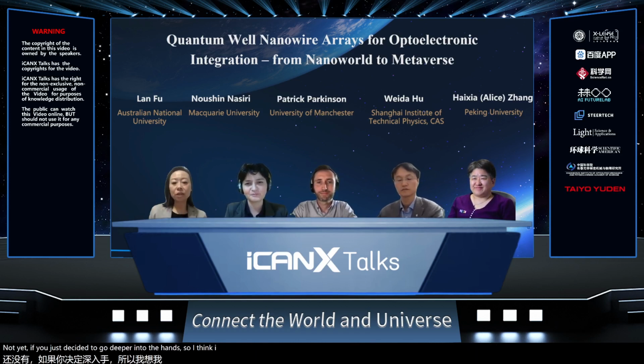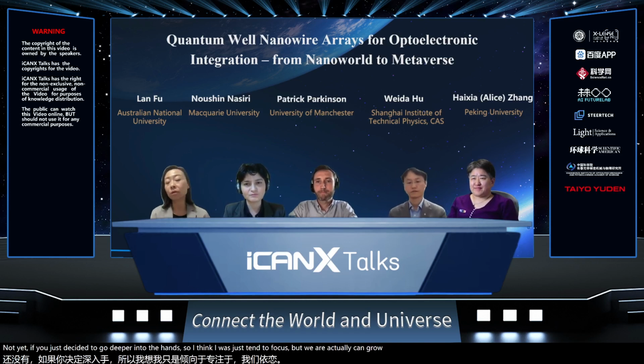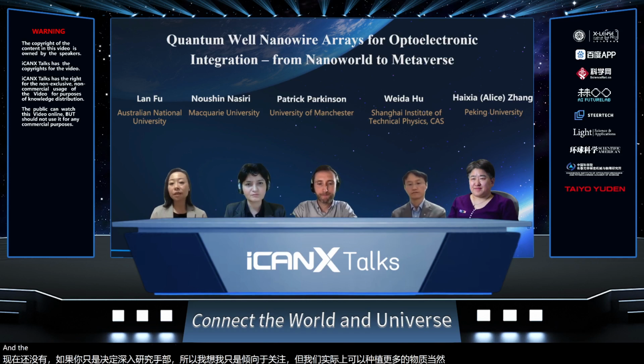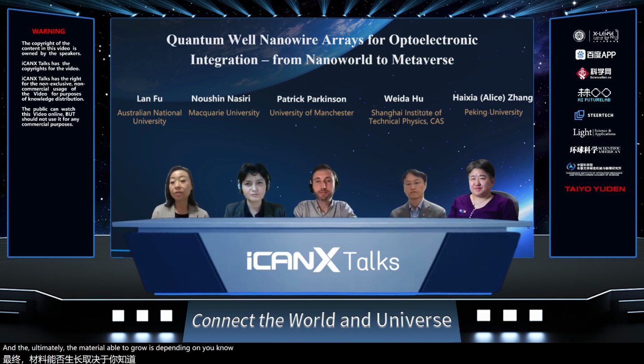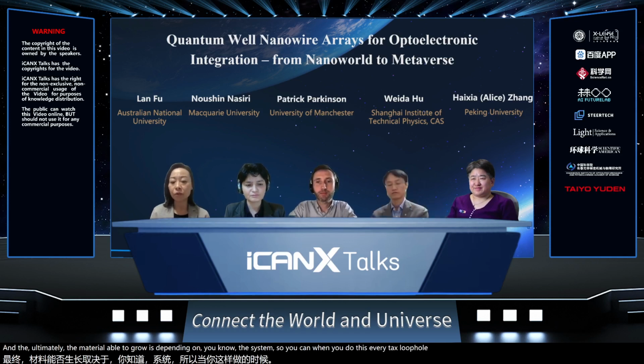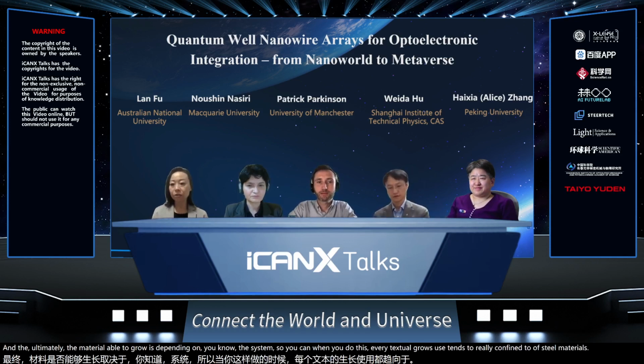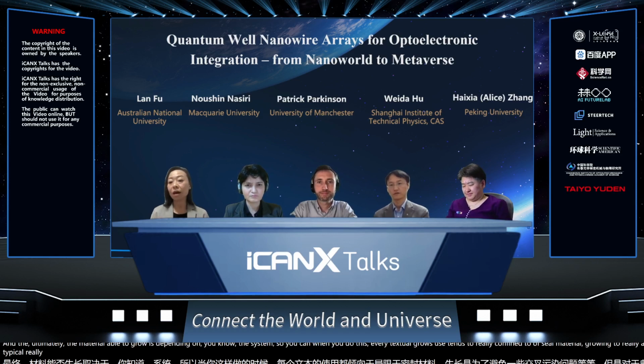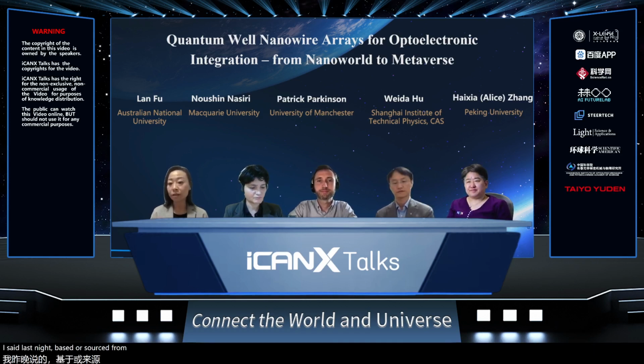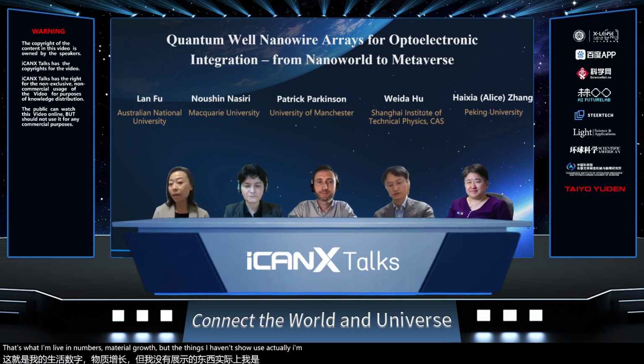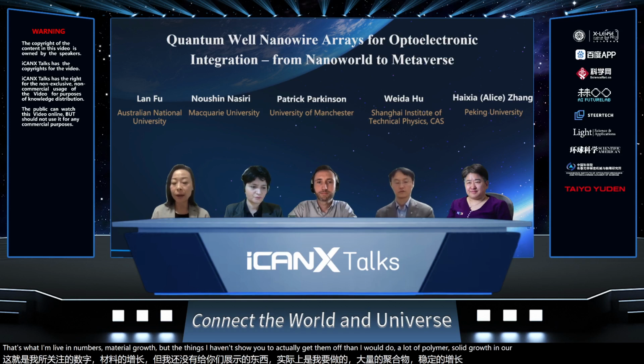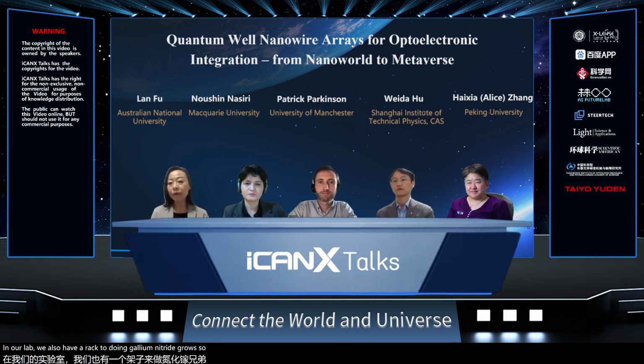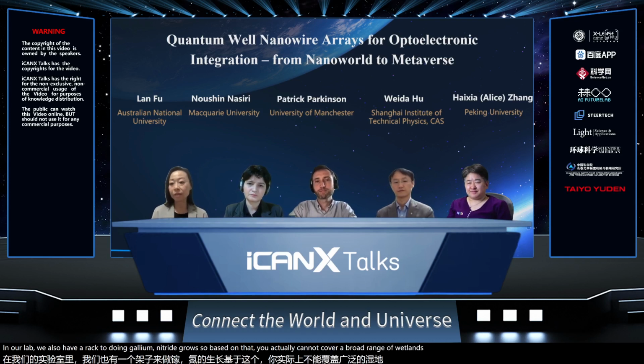Yes, I just tend to focus, but we can actually grow a lot more materials than that. Of course, ultimately the material you're able to grow depends on the system. When you do this epitaxial growth, you tend to confine to a few materials to avoid cross contamination issues. But for typical arsenide-based or phosphide-based materials, there's a limited number we grow, but the one I haven't shown you is gallium arsenide. We do a lot of gallium arsenide growth in our lab. We also have a reactor doing gallium nitride growth. So based on that, you cover a broad range of wavelengths and applications.